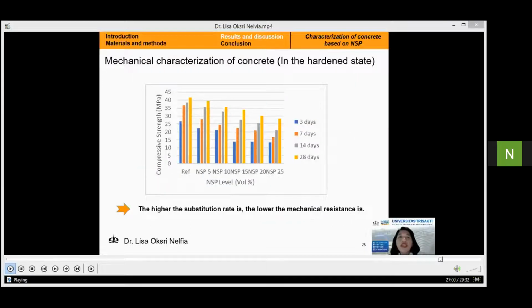The influence of NSP on the compressive strength is based on the data provided in this figure. This research concludes that the compressive strength for the 20% partial cement substitution is f'c 30 MPa at 28 days. Above 25% substitution of cement, the compressive strength is below 30 MPa, and so below the compressive strength referred.